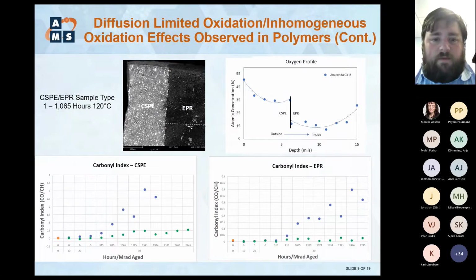This is another example of the same diffusion limited oxidation effects we're seeing. We're looking at Hypalon here in EPR. So this is a dual layer insulation with an EPR base layer with a CSPE jacket material, or overlaying material, essentially bonded to it.